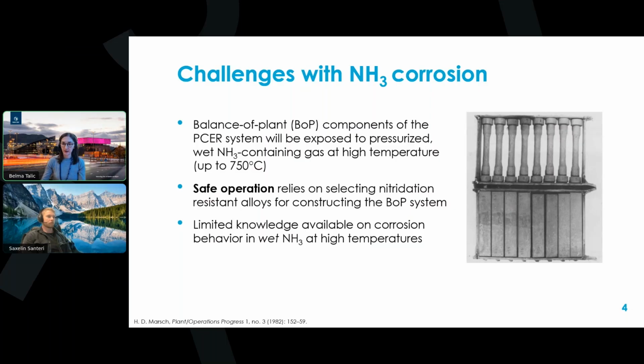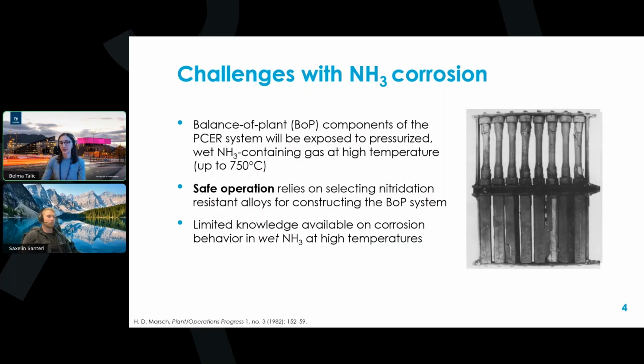There's a lot of knowledge out there available on the nitridation resistance of alloys from, for example, ammonia synthesis and nitriding of steels. But most of this knowledge is based on dry conditions and also at slightly lower temperatures than the maximum operating temperature that we are aiming for in SINGLE. So one of the key tasks of the SINGLE project was to identify alloys which were able to tolerate the specific operating conditions that we have so that we can operate it safely.